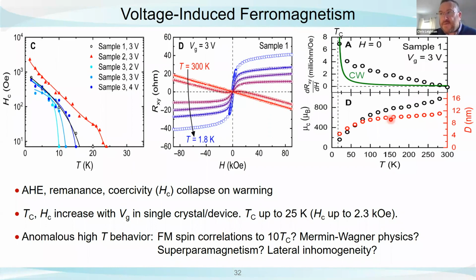But if that is the right way to think about it, then what we have here is a blocking point, and we would have some, I believe, lateral inhomogeneity in the gating process that would be needed to make that. You can work out what the size of the clusters would be if they're 2 nanometers thick. They've got to be about 10 nanometers wide. So in this picture, there is inhomogeneity laterally on something like a 10 nanometer length scale.